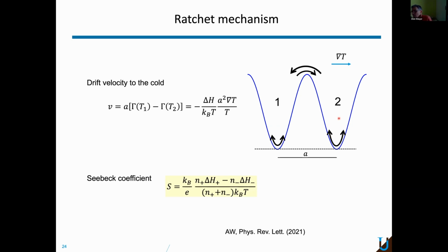So at some temperature, your particle takes up the energy of a fluctuation, gets over the barrier, gets down on the other side, and releases the energy on the other side. That means this is really the enthalpy of transport, because you really take this enthalpy, delta H, essentially to the other side. And so this is very general from the second law. It tells you very, very generally.